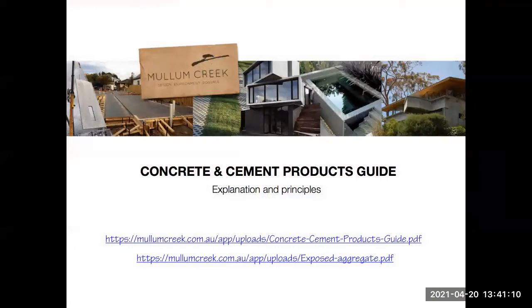The Mullum Creek design guidelines require that SCM make up a minimum 30% of the cement used in wet mix structural concrete, and some architects and builders have chosen to increase that to up to around 60% where surface finish is not so critical. As construction commenced on the estate, we found that more and more local batching plants were supplying concrete with SCMs with no increase to supply cost.